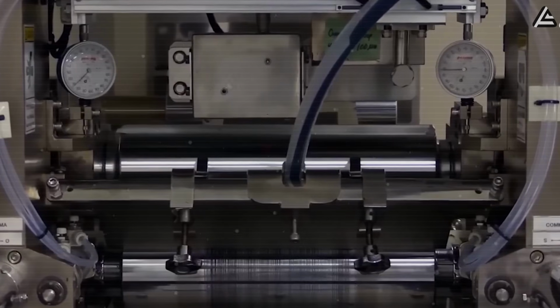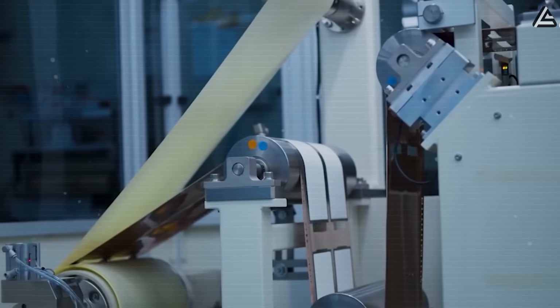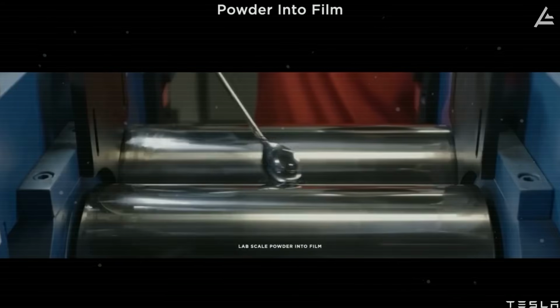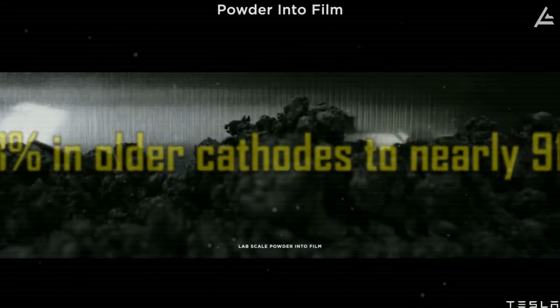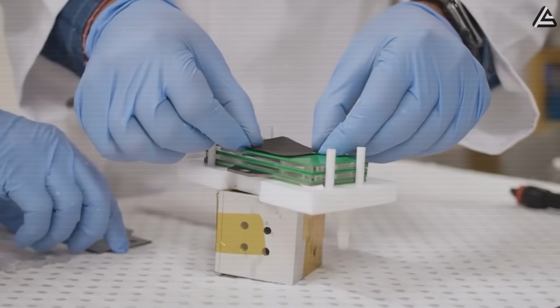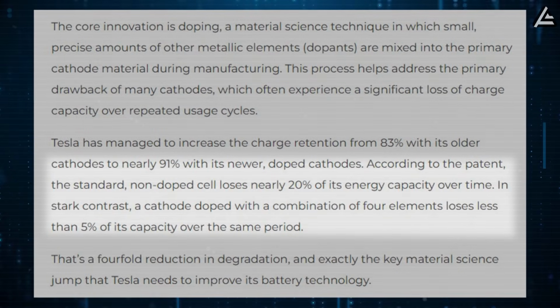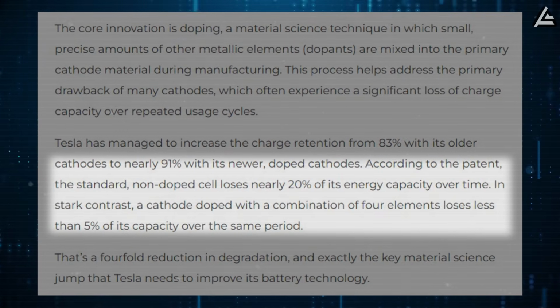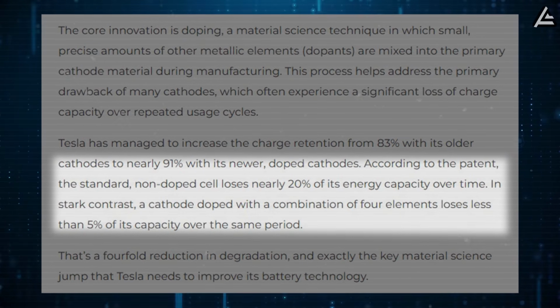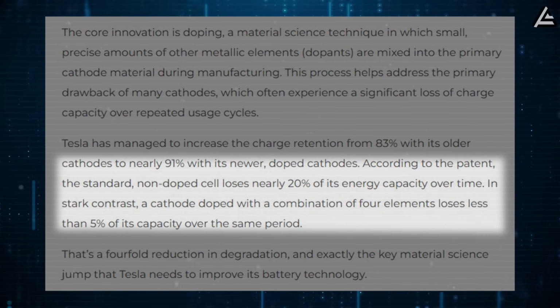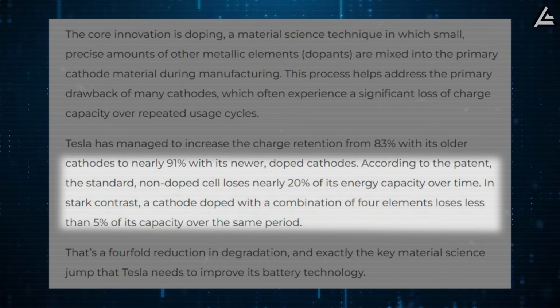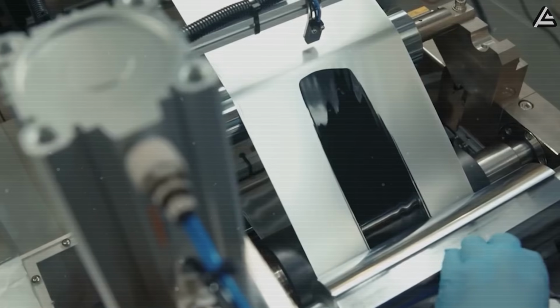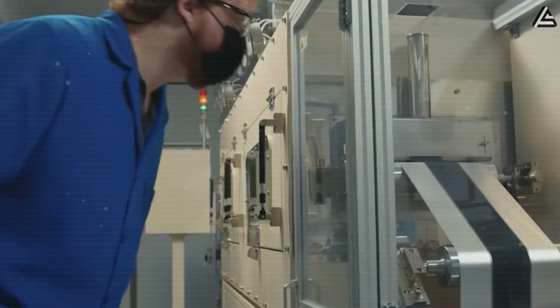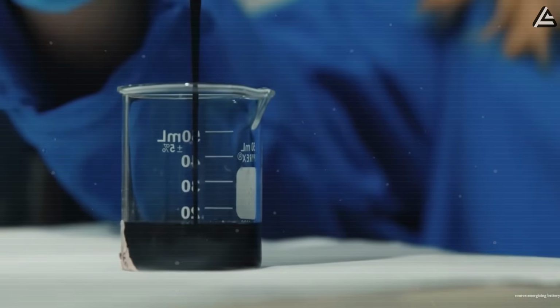This process directly addresses a major weakness of conventional cathodes, which often lose a significant portion of their charge after multiple cycles. With Tesla's approach, charge retention jumps from 83% in older cathodes to nearly 91% in the new doped versions. According to the patent, a standard, non-doped cathode loses almost 20% of its energy capacity over time, whereas a doped cathode combining 4 different elements loses less than 5% over the same period. This fourfold reduction in degradation marks a critical step forward in Tesla's battery science.